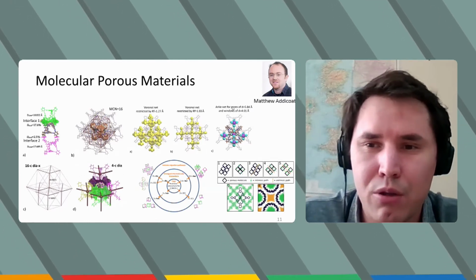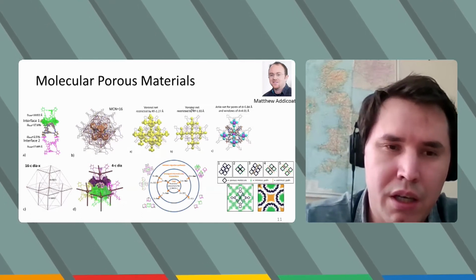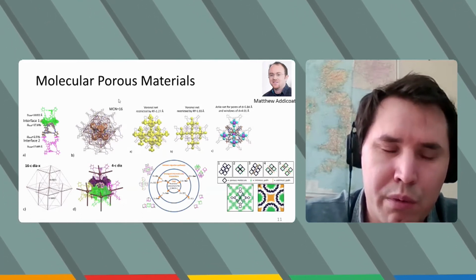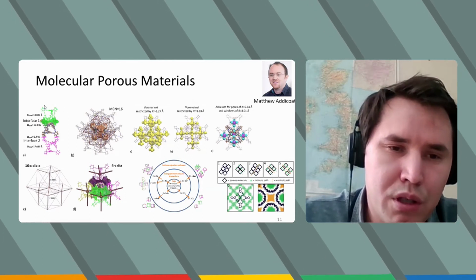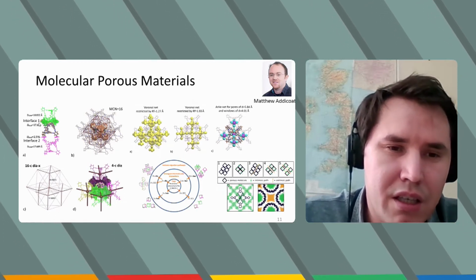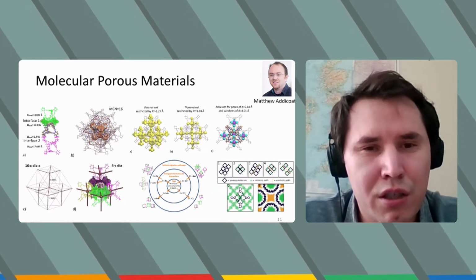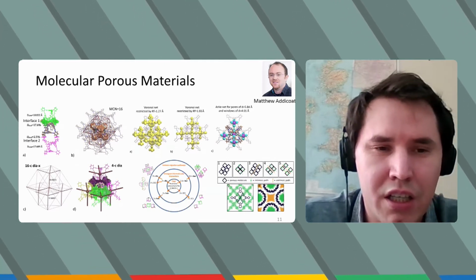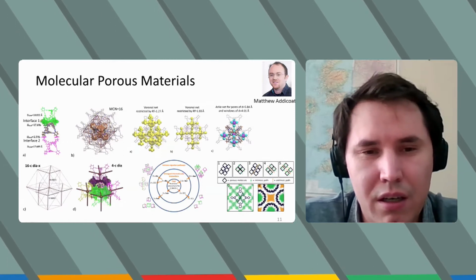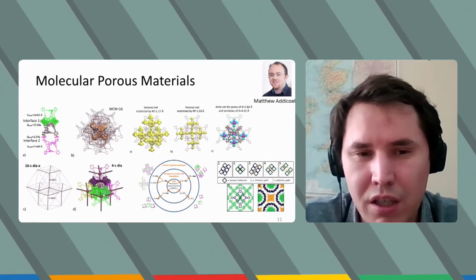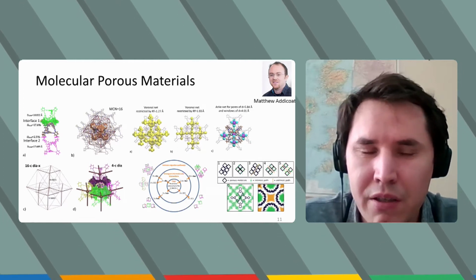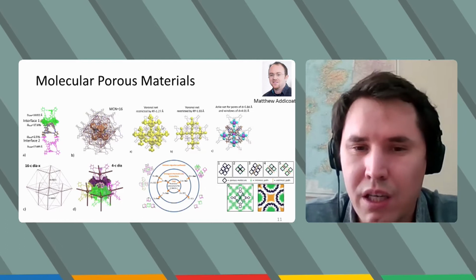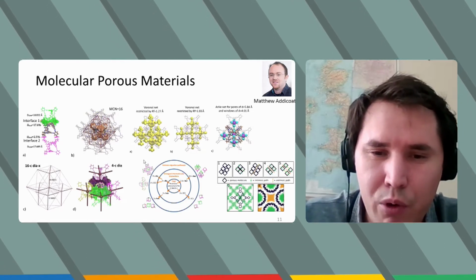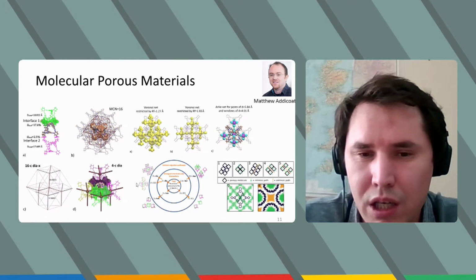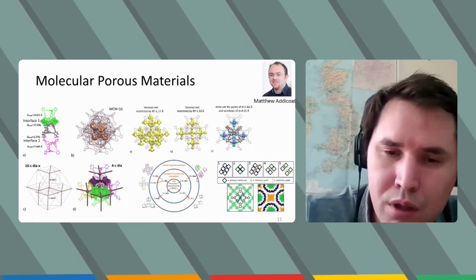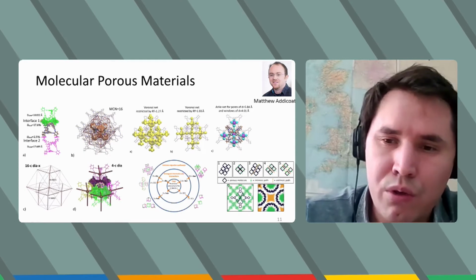Another project we developed together with Matthew Addicoat from Nottingham Trent University, and it is devoted to molecular porous materials. Using our new approach, we can estimate the shape of so-called cages, the interactions between cages, the motive of packing of these cages in crystals, and also migration pathways through the pores of this cage. And finally, we propose new correlations which were not discovered before, and these correlations can be used for prediction of new materials.